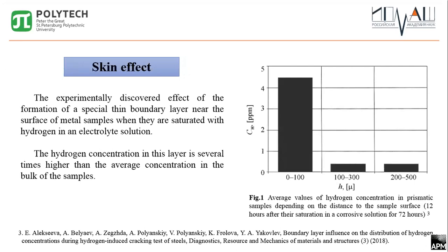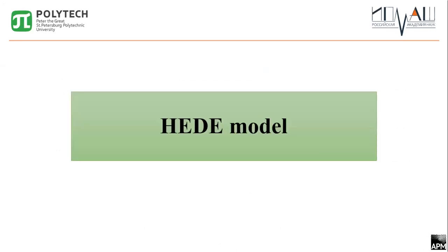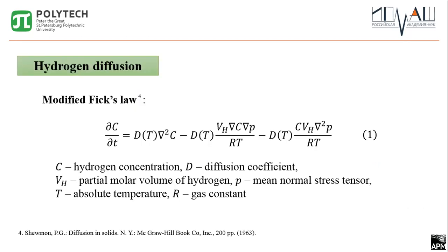hydrogen induced fracture. From the comparison of the HELP and HEDE approaches, it follows that the HEDE mechanism corresponds to the concept of brittle fracture observed in steels at high hydrogen concentration. Therefore, the use of this mechanism in describing the influence of the skin effect on the crack growth should provide an acceptable model for the destruction of hydrogen charged samples.